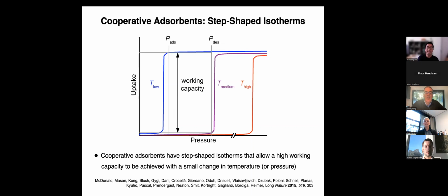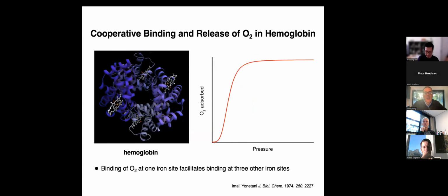And that means that you could do then a very small pressure drop to release the CO2, or if you're doing a temperature swing, a small temperature increase. And so this would be a big advantage, but it had never been realized in a dense way in a porous material. And there are a number of ways you can create stepped adsorption isotherms for adsorbents, but the way you'd like to do it is with cooperative binding, akin to how hemoglobin